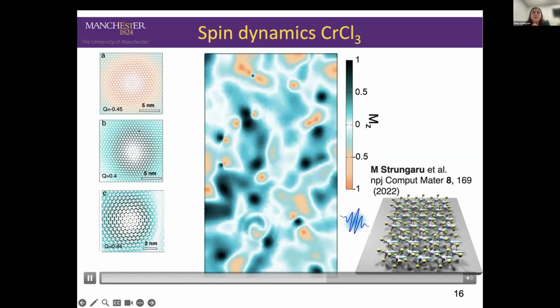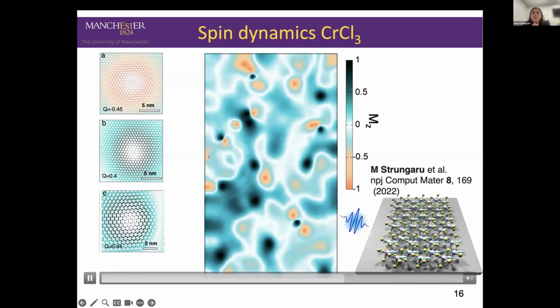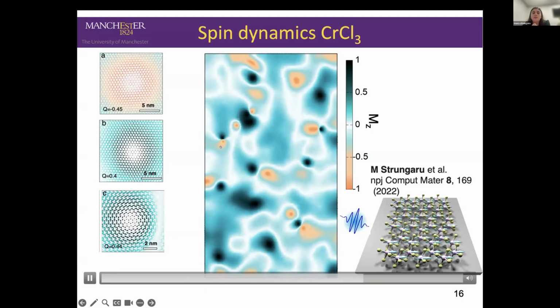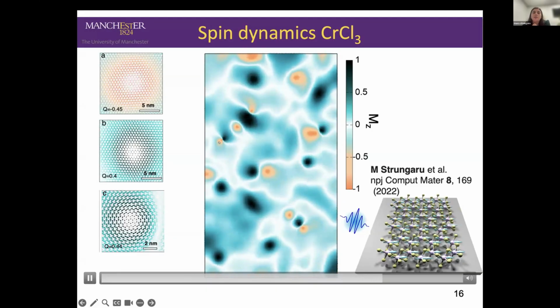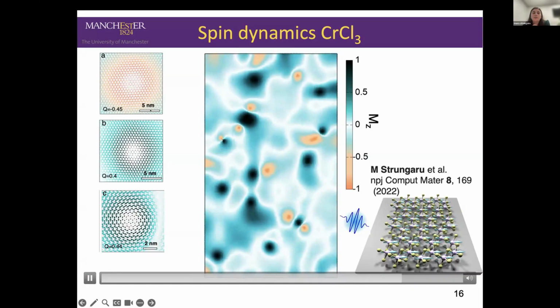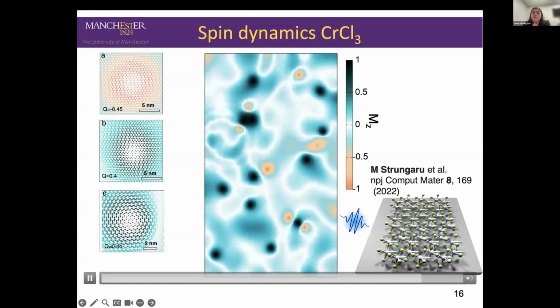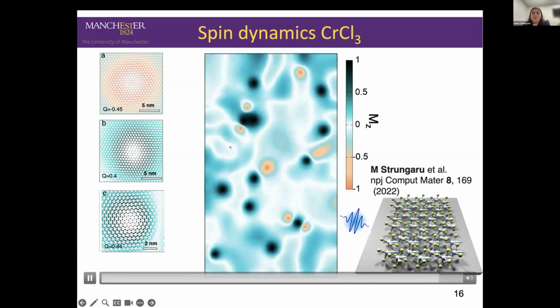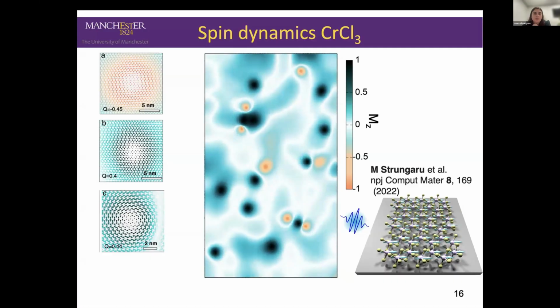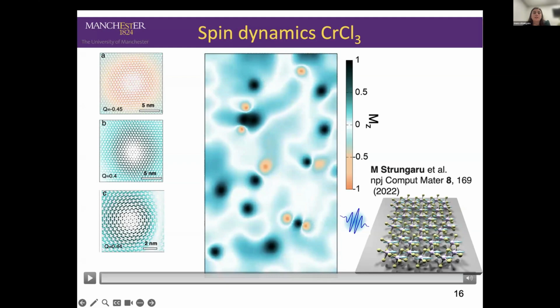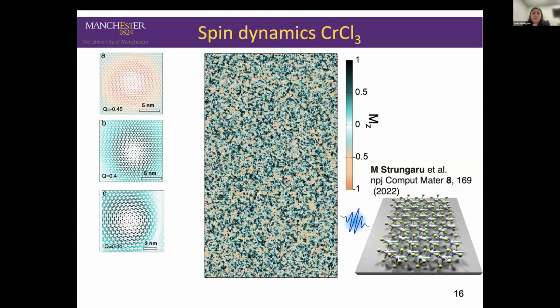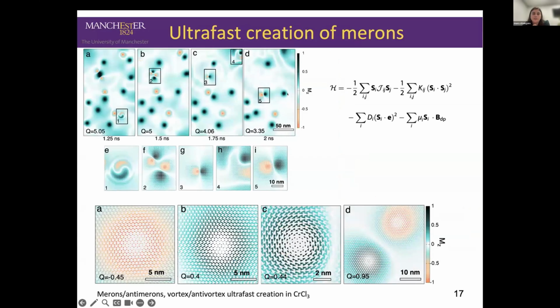If you zoom in, these are vortex, anti-vortex structures. But interestingly, you can also observe annihilation of these structures and emissions of spin waves during this process. So by using a laser pulse, we are able to nucleate vortex, anti-vortex structures, merons, anti-meron structures, and observe very rich dynamics in the systems.